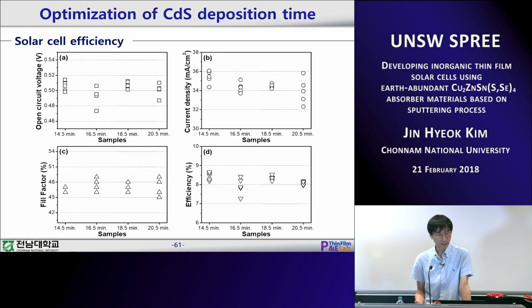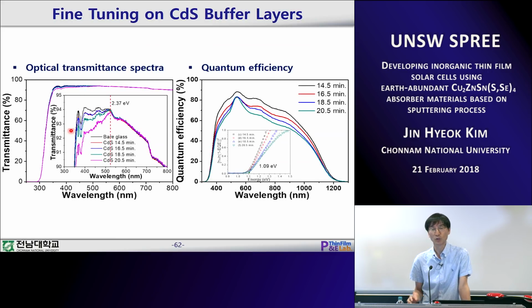so the cell efficiency of those four different samples shows that we have the highest cell efficiency with this very thin layer. So at this time, we conclude that if we can get a very thin layer, we can have a higher cell efficiency, because when we checked the optical transmittance, we saw that with decreasing buffer layer thickness, we could improve the transmittance in the very short wavelength region. That means we could get more light into the absorber layer. So that gives more photon generation, like charge carriers.